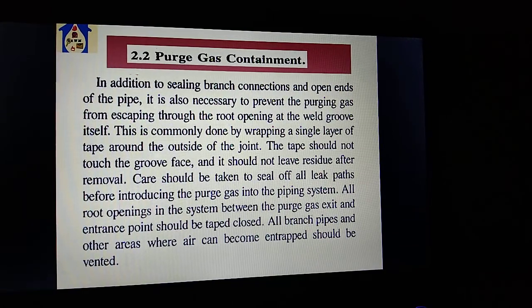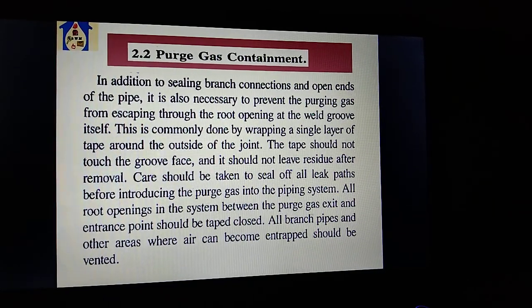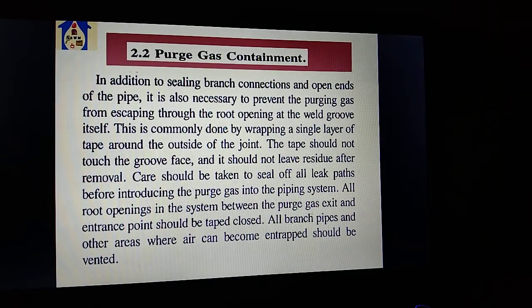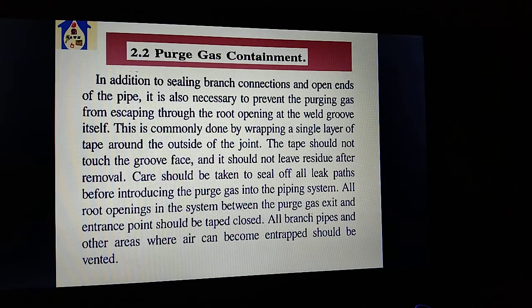In addition to sealing the branch connections and openings of the pipe, it is also necessary to prevent the purge gas from escaping through the root opening at the weld groove itself. This is commonly done by wrapping a single layer of tape around the outside of the joint. The tape should not touch the groove face. It should not leave residue after removal.